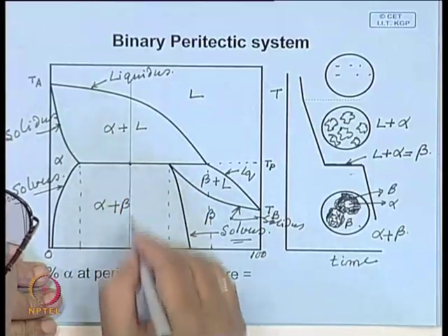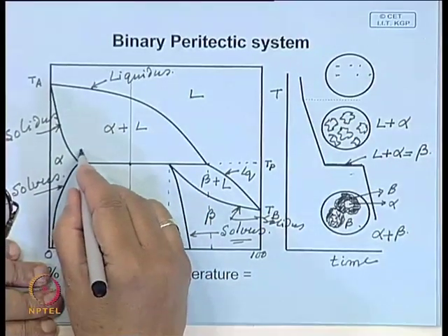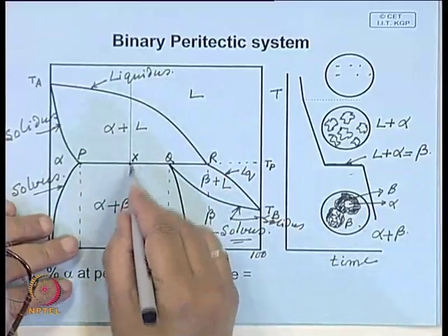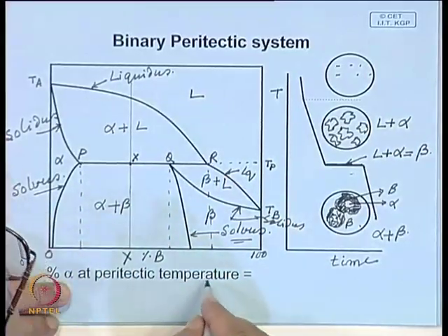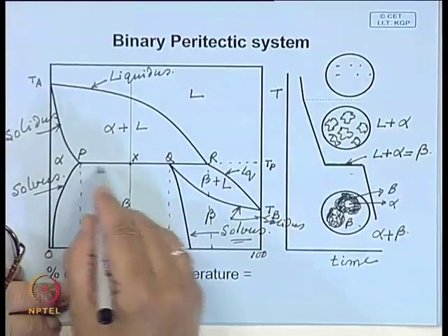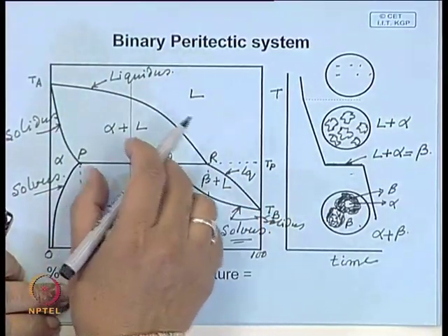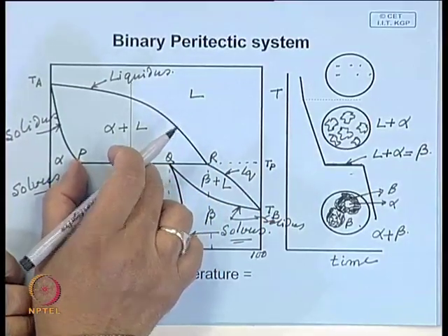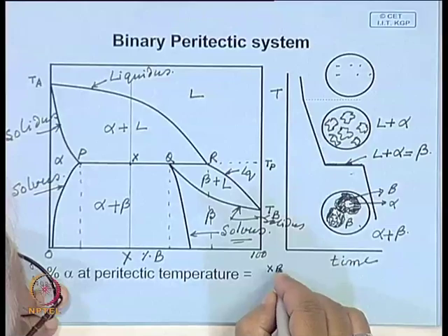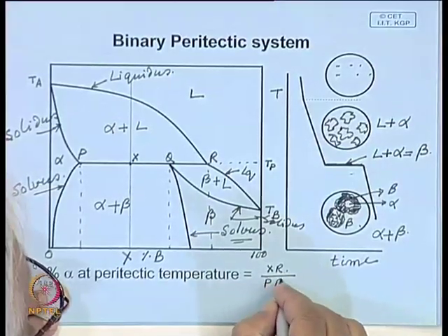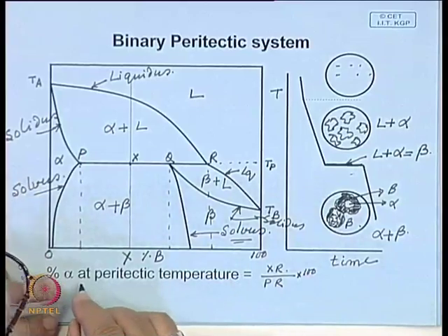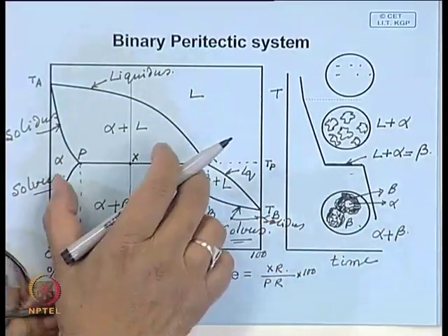So, here if this composition is X, and here if you say P, this point is X, this point is Q, let us say this point is R, then the percentage alpha at peritectic temperature, just before solidification, the amount of liquid is proportional to P x, and the amount of alpha is proportional to x r. So, this is x r over P r. This into 100 will be the percentage, so this will be the percentage alpha at peritectic temperature, x r over P r,